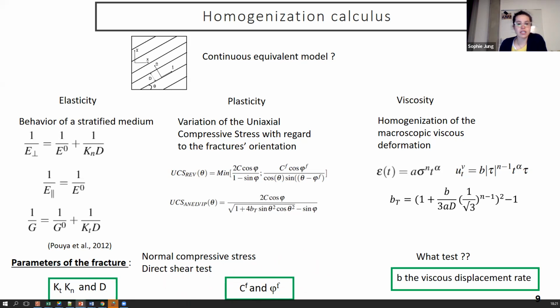The plastic behavior is completely determined by the apparent cohesion and friction angle of the fracture. So it is also possible to determine them by direct shear test. And the last parameter that remains is the viscous displacement rate. And this is the more tricky part. It's not very clear what test to do to determine it, but that's also the point of my work, to find out how to measure it.